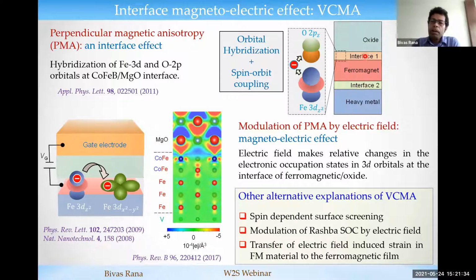Now, when you apply the electric field at this interface by using a gate electrode, what happens? Basically, the number of electronic occupation states in the out-of-plane 3D orbital is changed with respect to the in-plane 3D orbital, and that relative change can induce a change in the anisotropy in the spin system. That's how you can change the anisotropy by electric field.